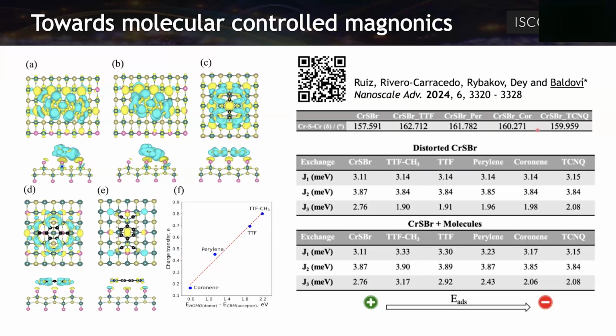This is just the effect of the structure. But another thing is the effect of the charge transfer. So if we calculate just the distortion of the chromium sulfur bromide, we can observe here in J3 that 2.8 is the J3 in millielectronvolts for the chromium sulfur bromide, but this is clearly decreased by the effect of this change in the sulfur bonds between the chromium along this direction. But then when we activate, because here we are removing the molecule from the calculation, just taking the distortion, when we activate in the calculation the atoms that come from the molecule, there is the charge transfer, and we increase clearly the J3, especially in the case of the TTF-CH3, but also it is increasing in the case of the TTF. So this is the effect by the charge transfer directly. We can compare these two calculations.